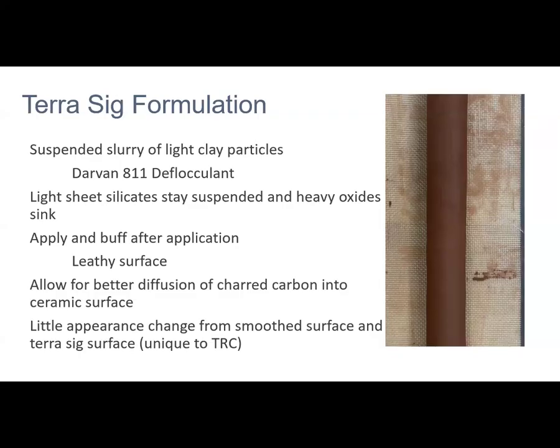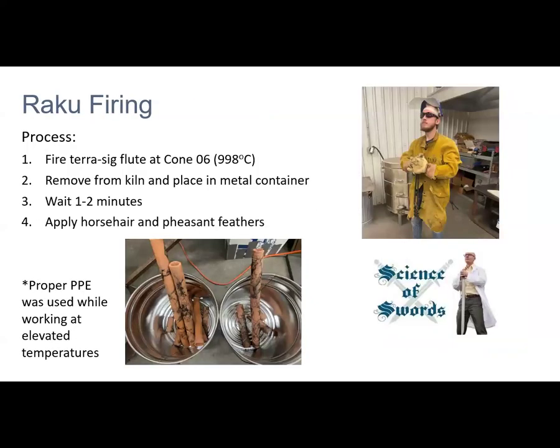They did a formulation. It's a slurry, and they used a deflocculant, to help the silicates stay suspended and the heavy oxides to sink, and they applied this to the surface, and it helped give it a leathery surface, the idea being better diffusion for the charred carbon in the ceramic surface. So they were prepping it for that raku firing was what they were doing here.